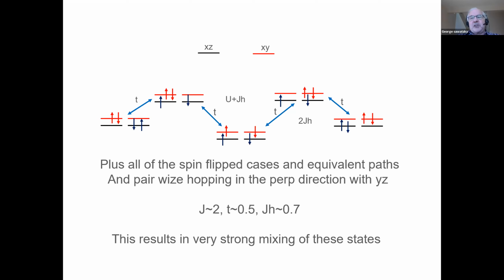Well, I showed you pictures in LDA plus U with LSDA, where you actually have 3 Bohr magneton magnetic moments. Depending, but then the lattice is also very stretched. It would automatically want to stretch, and the selenium would want to come down almost into the iron plane. You'd almost get a rock-salt-like structure in the end. But these moments we feel are really quite large. What we get is something close to 2 Bohr magnetons, which means a spin of 1, right?